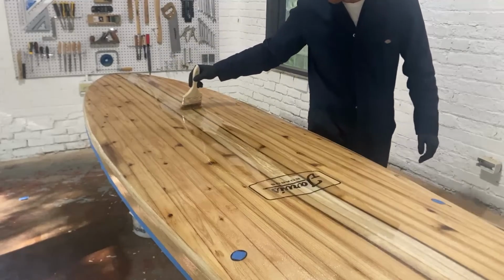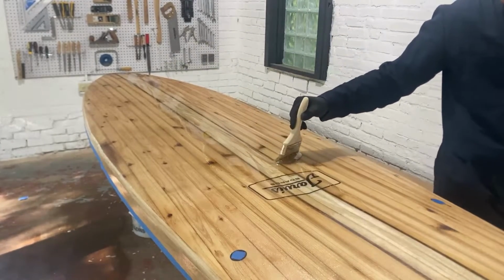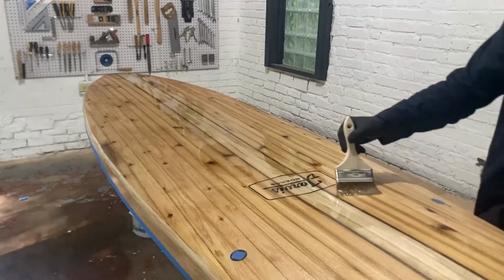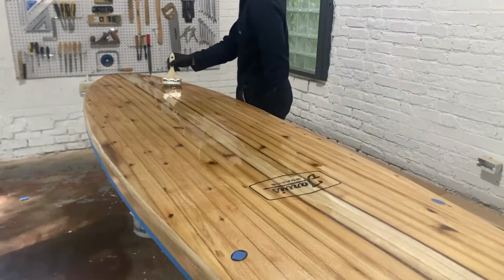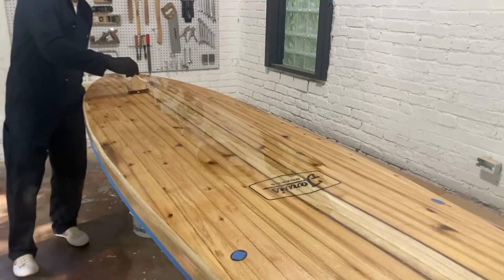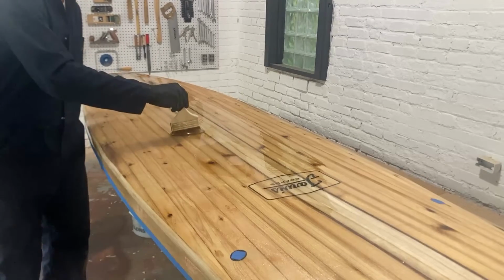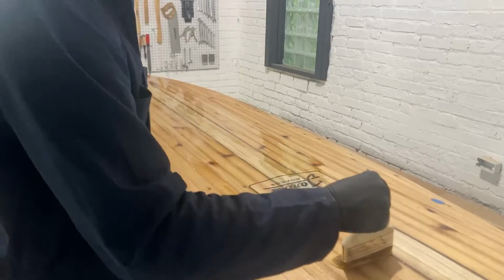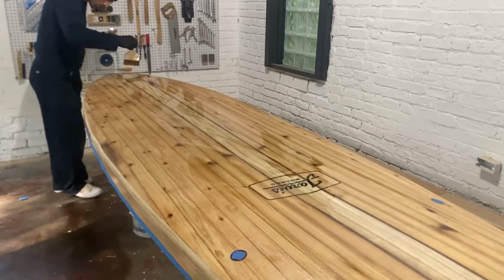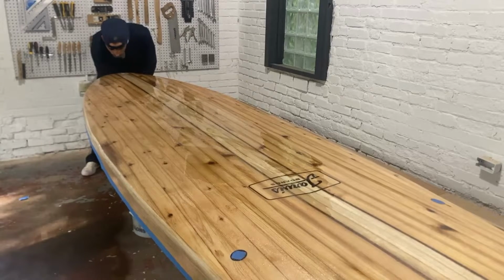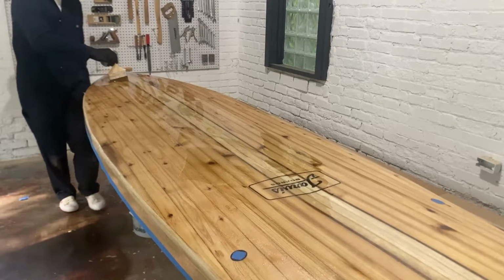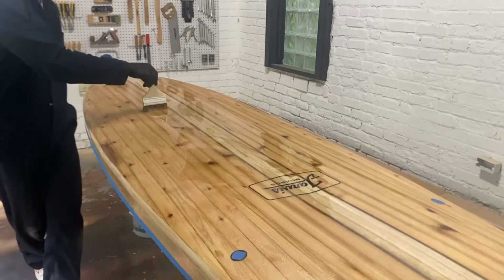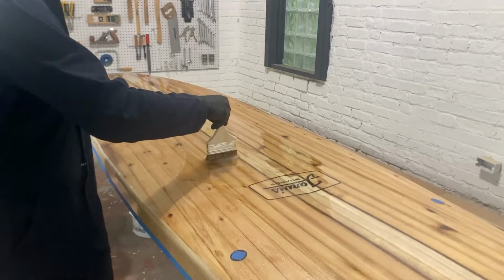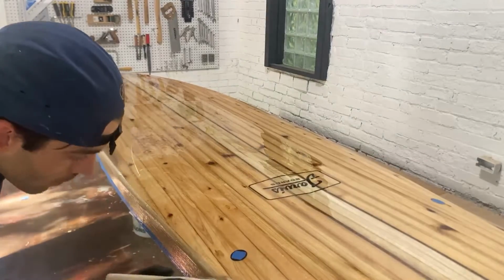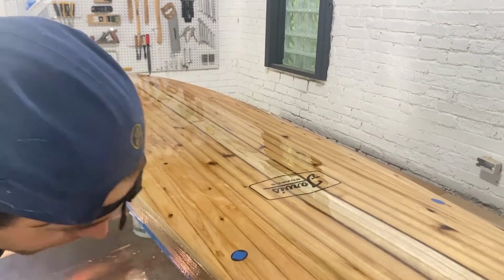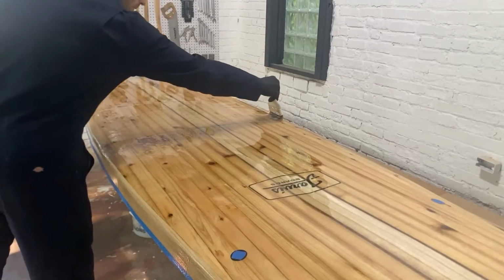After everything is cured, if you notice those tiny little bubbles that I talked about earlier forming as the epoxy starts to cure, don't freak out and try popping them all with a heat gun or a torch or more brush strokes. Trust me, that will likely just make matters worse. My recommendation is to lightly sand these bumps down after it's fully cured with some fine sandpaper on an orbital sander, wipe down the board with a damp rag soaked in denatured alcohol, and apply another skim coat of epoxy. Sometimes these bubbles are so tiny and so close to the surface that you can skip that extra skim coat by lightly sanding the bubbles down, and the varnish that we apply at the end will cover them up.